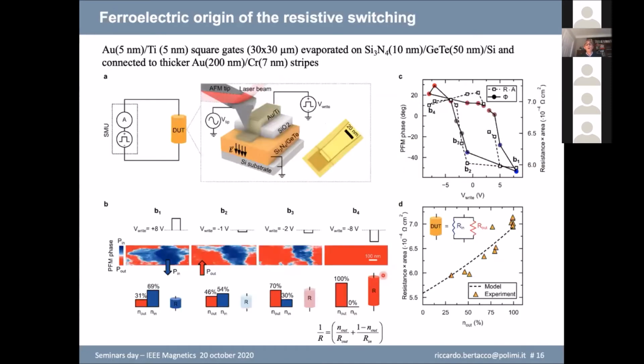And let's now move to this experiment, which is very relevant to me because it really demonstrates the connection between the ferroelectricity and what we are seeing in terms of the conductance change. This is a clever experiment carried out by Christian, in which he realized a device, this one with the silicon nitride germanium telluride bilayer. And on top of that, you have your metallic gate electrode with a very thin layer here, which allows for a PFM measurement through the metallic gate, and another region in which you can apply a writing pulse. And by measuring by PFM the ferroelectric map in this region, he was able to see what happens when you apply different pulses, starting from plus 8 volts. Here you see the map of the piezo force microscopy phase.